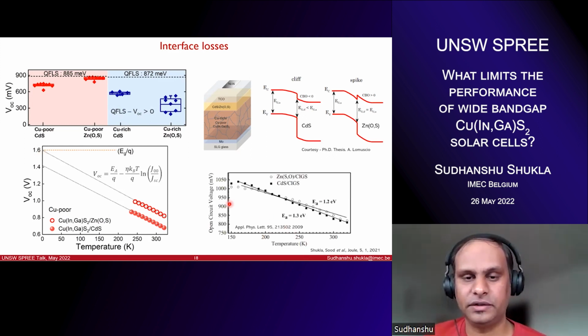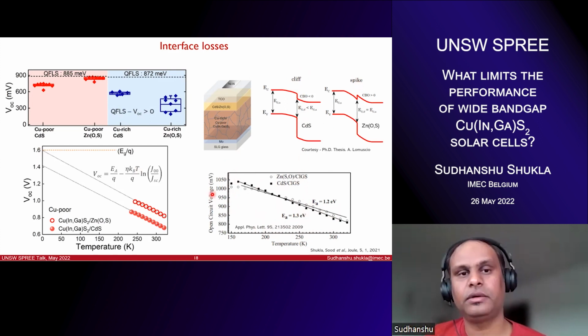If you refer to the literature of CIGS, it was done in 2009 that CIGS was made with cadmium sulfide and zinc oxysulfide both, and the activation energies were actually less than the band gap, which means even after replacing the buffer, going from cliff to spike, you do not solve the problem of interface recombination. You have to switch from copper rich to copper poor. Then only you can solve this problem.